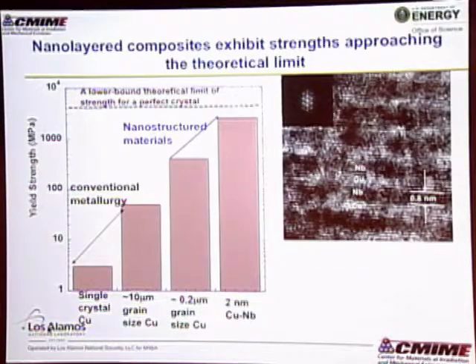So what happens if we put a whole ton of these boundaries into the material? Well, we get this plot that we can see right here. These are different types of copper-based materials, and this is what their strength is. If we talk about a single crystal of copper with dislocations in it, the strength is extremely low, a couple of megapascals in this case. As we start introducing grain boundaries, that is, having a grain size of 10 microns, this is like the copper that you buy at the hardware store. You'll get a strength right about here, about 10 times higher.